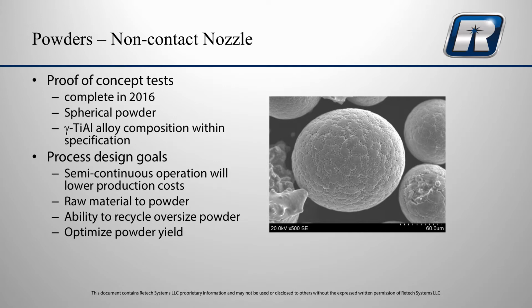We're also looking at other areas and other ways to produce powder via what we call a non-contact nozzle. We did some proof of concept tests last year and completed those in 2016. And we made spherical powder out of a gamma titanium aluminide composition shown on the right. The actual composition was TNM. And our process design goals were we wanted a semi-continuous operation with low production costs. And we wanted to be able to take raw material and convert it directly to powder.